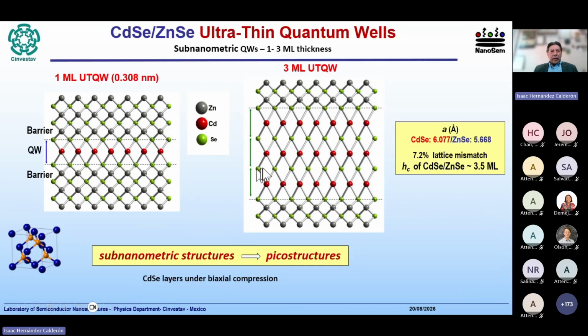So one of the systems that has attracted our attention are the ultra-thin quantum wells. These are very interesting systems, extreme exotic systems that are formed just by a few atomic layers. I will use as an example cadmium selenide, zinc selenide quantum wells. We can go from 1 to 3 monolayers. We cannot go to thicker films because the critical thickness of these systems is 3.5 monolayers. So most of the work is done with these ultra-thin quantum wells that are, in fact, subnanometric